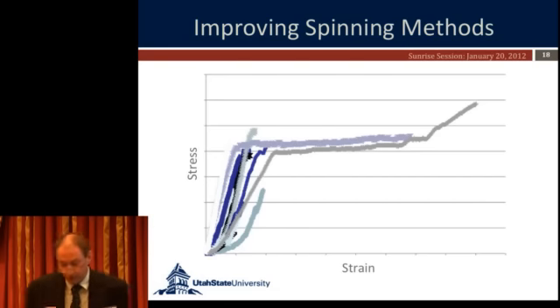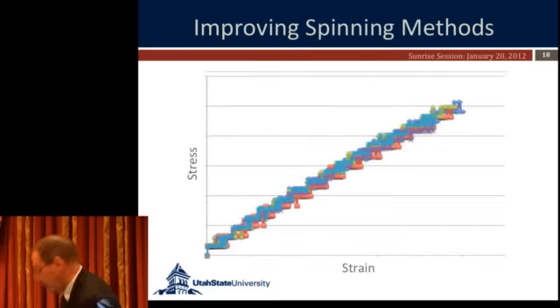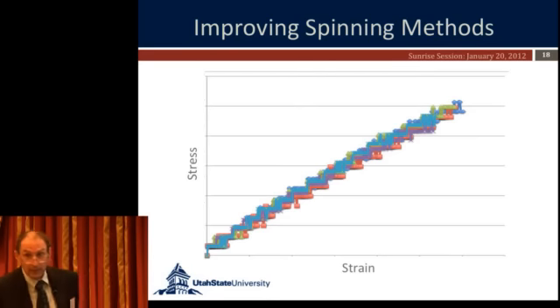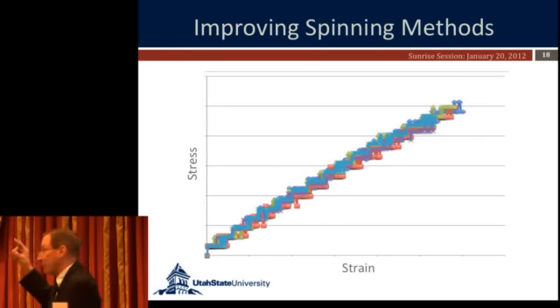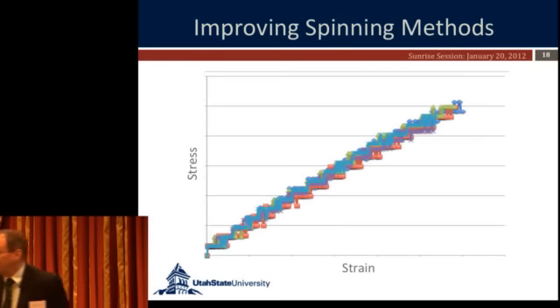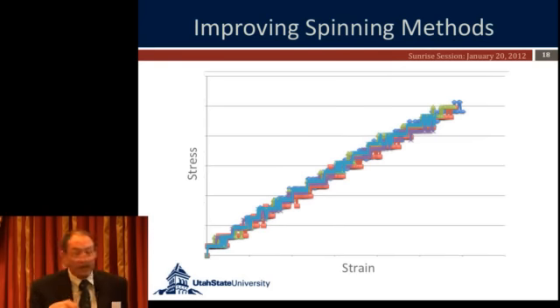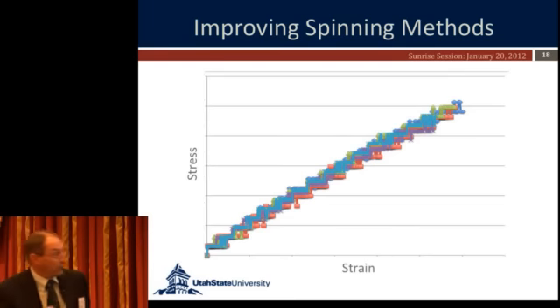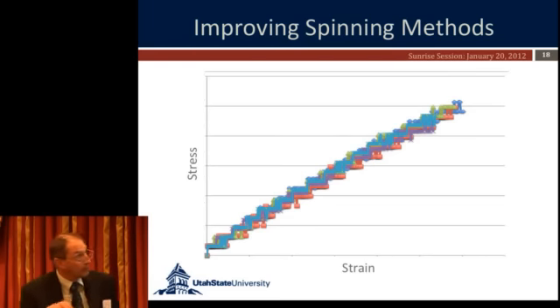Since we moved to Utah State in June, we've actually figured out how to solve that problem. And so here's an example of what happens now, and you can see that every one of the fibers, and there's only 5 of them here, the total study had 20, but you know what happens when you put all the colors together? I learned that in art class. What color do you get when you put them all together? Brown, right? So the only thing you'd have seen was a brown line here, and you wouldn't have known anything, all right? So we only use 5 here so you can see that all 5 of them look exactly the same. If I put 20 there, you wouldn't have been able to tell anything in terms of that.